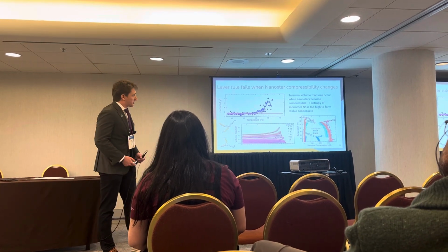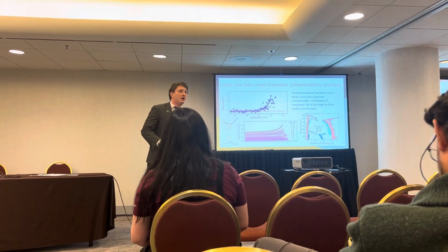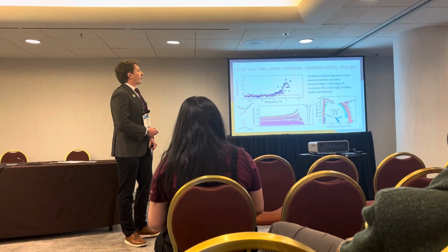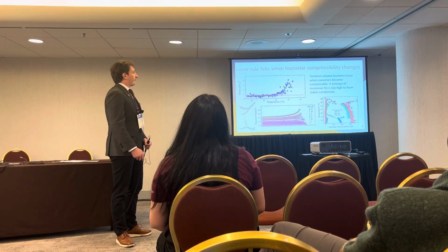These forbidden volume fractions that we've seen, or terminal ones as I've introduced them to you, likely arise as a result of the entropy of the monomer being too high to justify the energetic cost of forming a highly dense condensate. And for completeness, these three well-resolved phase diagrams are presented on the same axis over here, just because I think it's a very pretty plot personally.